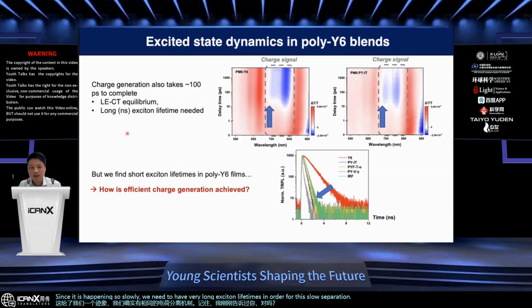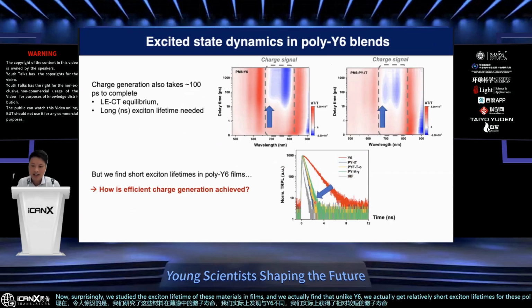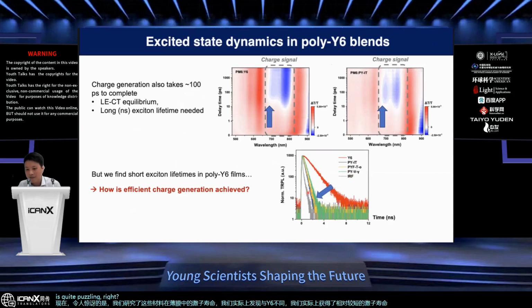in order for this slow separation to be efficient. Now, surprisingly, we studied the exciton lifetime of these materials in films, and we find that, unlike Y6, we actually get relatively short exciton lifetimes for these polymerized acceptors. And that was quite puzzling. If they live for only a short time, then how can we have such efficient, slow separation?